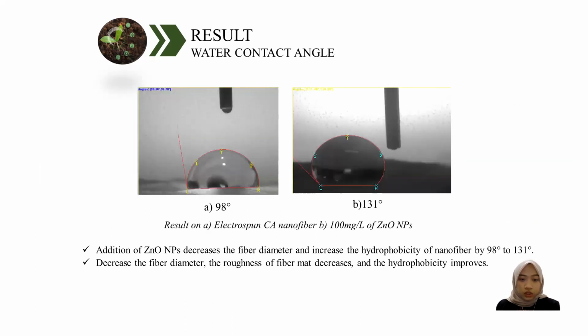As for the water contact angle, the zinc oxide nanoparticles, as explained before, decrease the fiber diameter and increase the hydrophobicity of the nanofiber from 98 to 131 degrees. It is favorable for seed coating because with the hydrophobicity of the material, it is able to control the release of zinc oxide nanoparticles for a long period of time and reduce the toxicity effects.